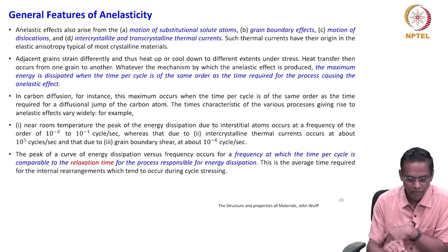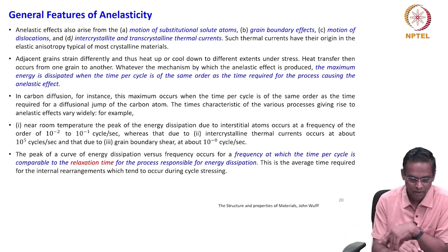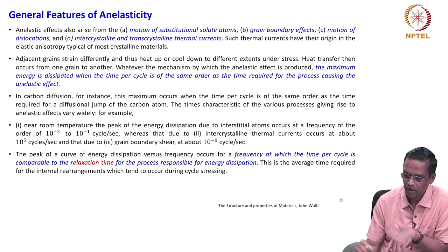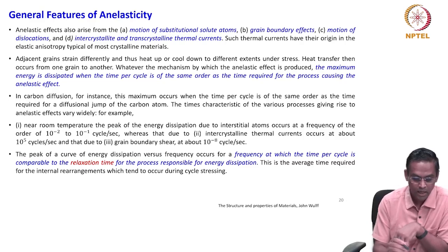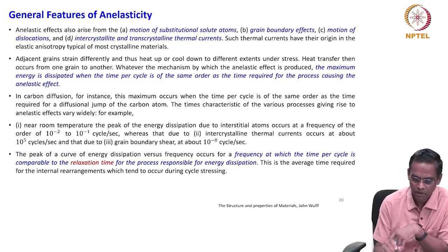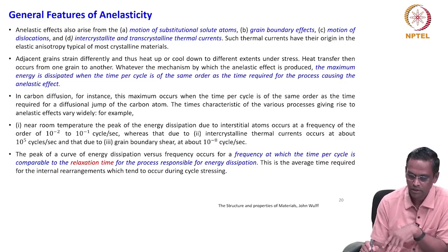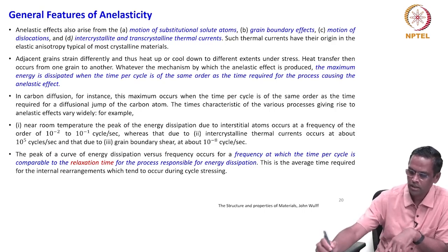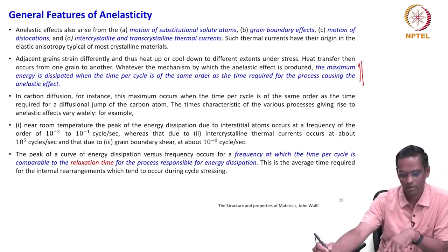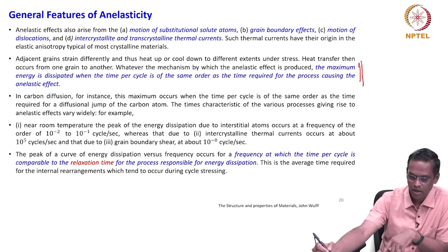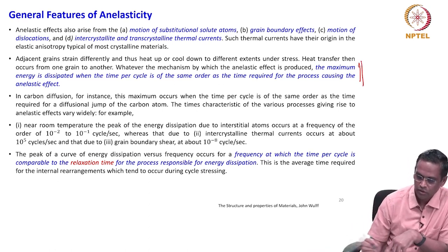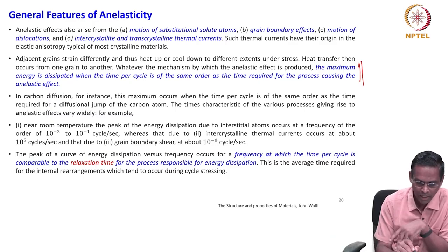The peak of the curve of energy dissipation versus frequency, this is what we have seen already, occurs for a frequency at which the time per cycle is comparable to the relaxation time for the process responsible for the energy dissipation. So, this point is almost what we have just made a statement about just before. Now, to have some more clarity, we are bringing another parameter called relaxation time.